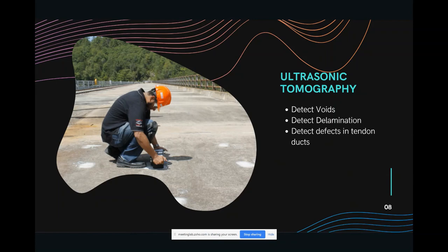Ultrasonic tomography is a great tool for detecting voids and delaminations in concrete elements. The technique has improved significantly over the last decade — initially limited to thickness gauges using pulse-echo, but now with improvements in mathematical modeling and signal processing, it can identify events that exist inside the concrete element. If you need to identify the location of voids, the location of tendons, or any major defect in the subsurface of concrete, ultrasonic tomography provides an excellent tool for collecting this information.